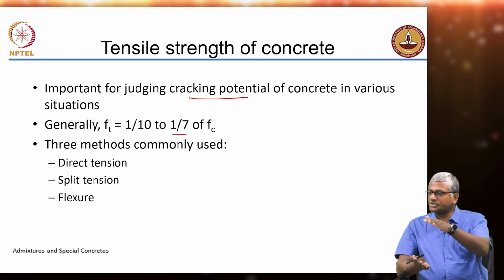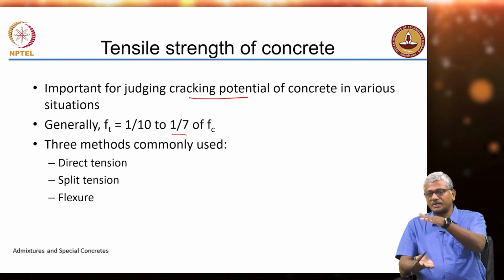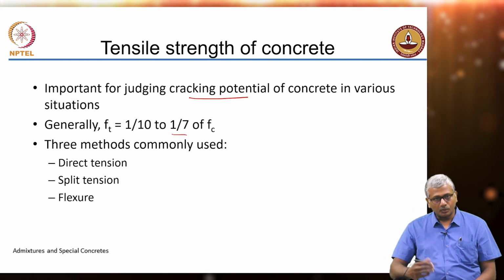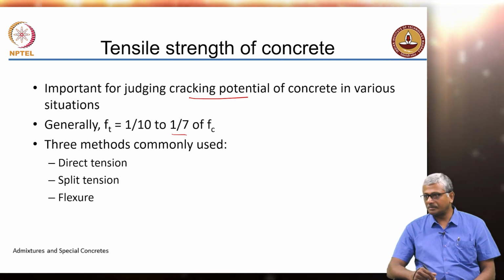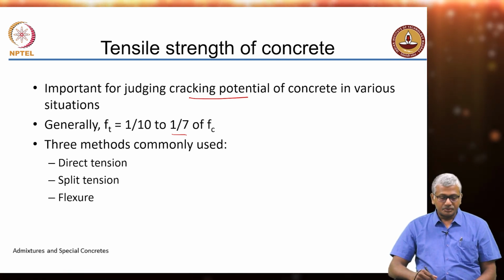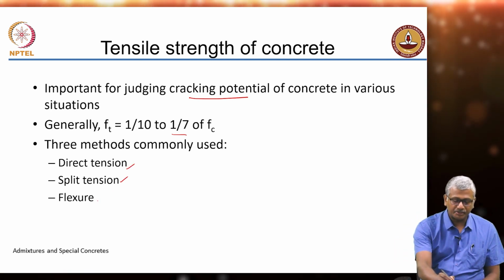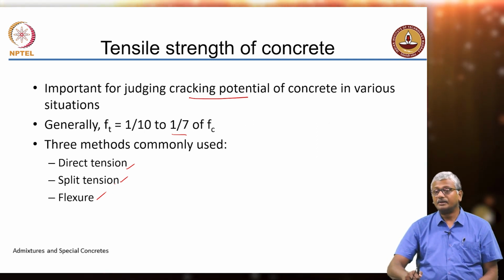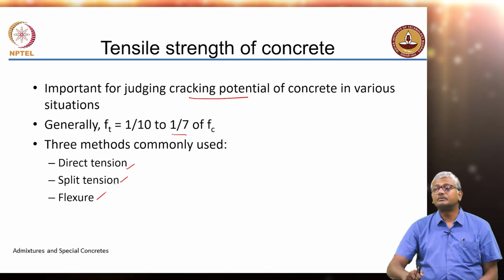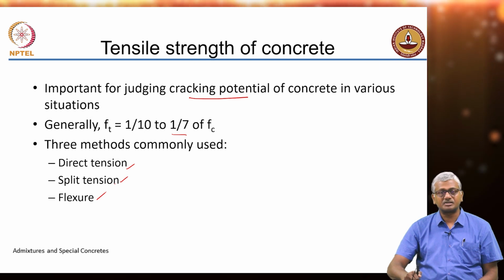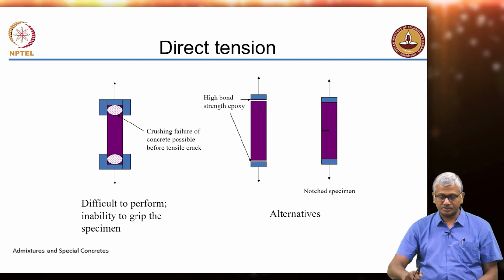If you do a split tension test, when you use a cylinder to test the split tension, you will get even lower strength than that, typically around 3 megapascals. So, we can use a direct tension, a split tension or a flexure test depending on the type of standard or specification that prescribes the choice of flexural strength.